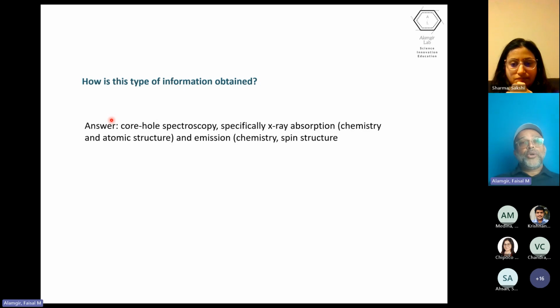Or the following event where the core hole that is left behind is then filled by another electron cascading down. And in that process of cascading down, a characteristic X-ray emission is released by that same atom. And so that X-ray emission now becomes a characteristic signal. All of these techniques carry chemical information. That is, the details of what type of chemical bonds are around that particular type of atom. Okay, so that's where the chemical information comes from. X-ray absorption is the unique one among these core hole spectroscopies, in that it also gives you atomic structure.